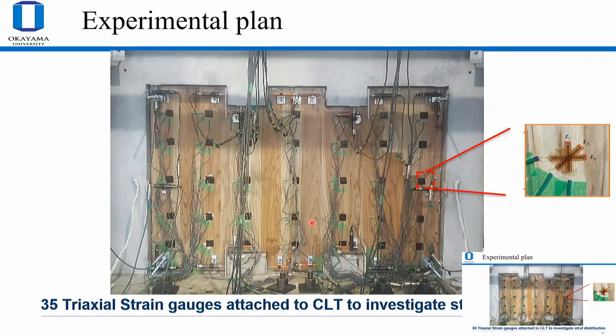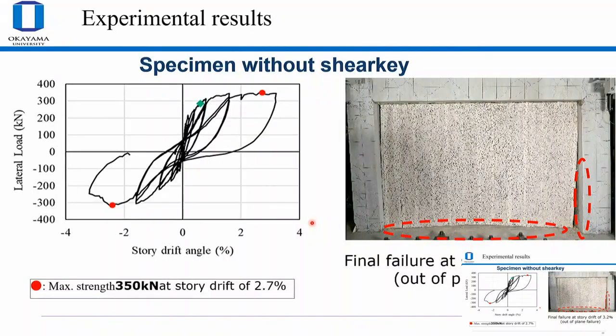Okay, so I'll go to the experimental results. First I'll show you the one without the shear keys. If you see here, at around 0.8%, the column yielded, and after that, at around 1%, it reaches almost maximum strength. After that, it goes almost straight. The maximum was around 2.7% story drift, around 350 kilonewtons. This is both RC and CLT. The RC frame alone is only around 150, so CLT is carrying around 200 kilonewtons.